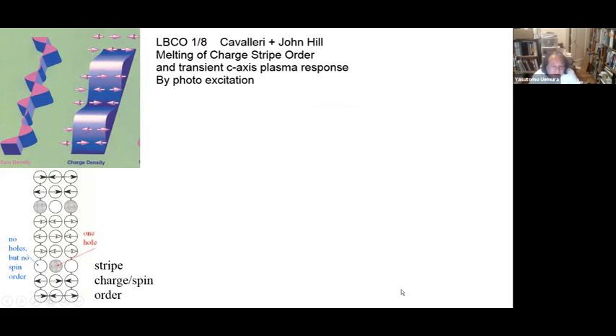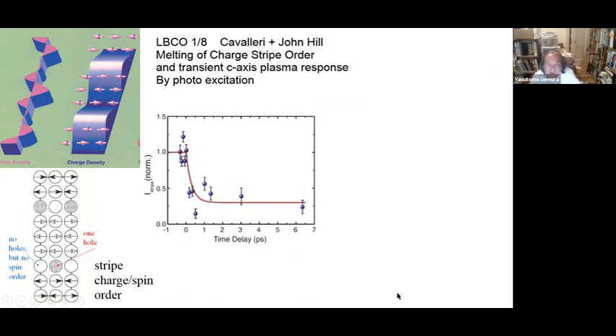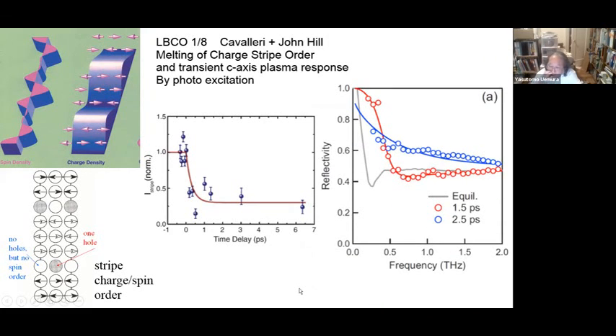Now, this is the stripes and their spin-charge correlated order. And Andrea again was able to melt this spin-charge order by light excitation. This is how the Bragg peak of that stripe is perturbed by the light. And he showed that laser excitation induces this reflectivity, a superconducting-like response, in a short time. Okay, so this is already showing that what light is doing is essentially killing the competing antiferromagnetic or stripe order and helping the superconducting order.